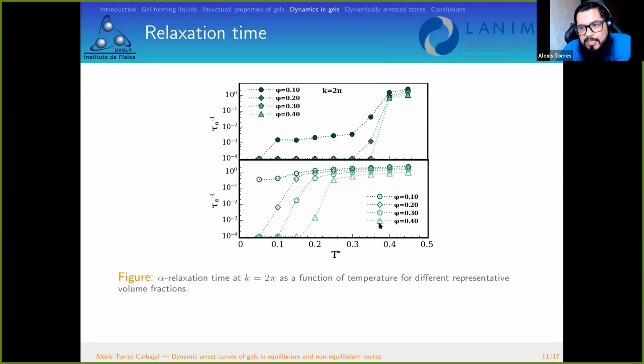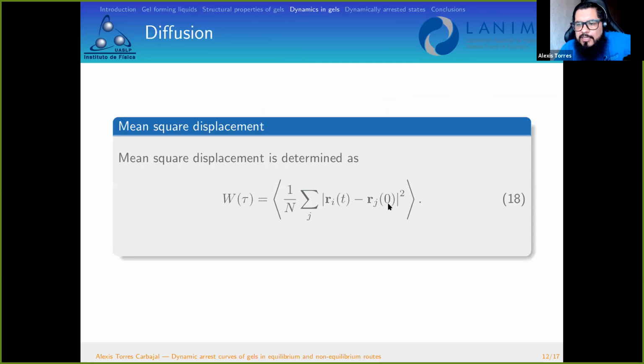But in the case of the Lennard-Jones with the Yukawa tail, we observe that this change takes place at different temperatures that almost depend, or we can assume that depend, on the density of the system. So this information is also corroborated with the computation of the diffusion.